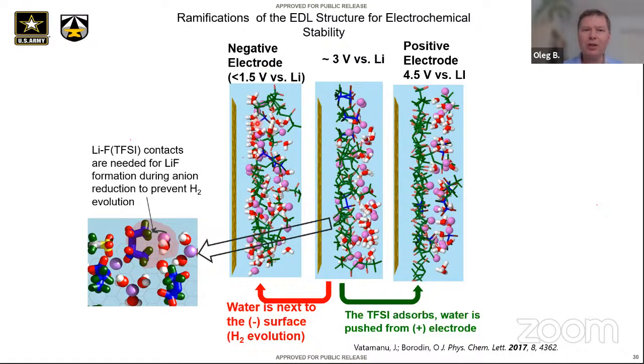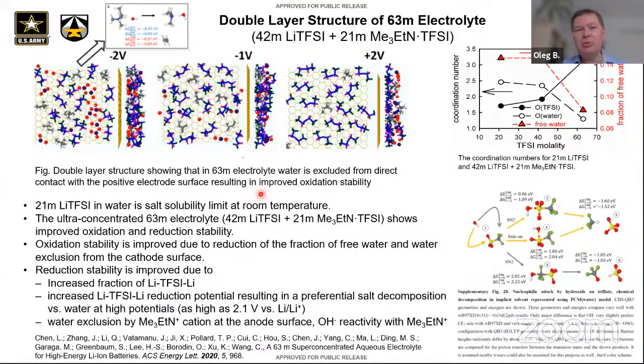However, on the negative electrode, especially if potentials are very negative, if you look at what the previous seminar speaker Axel talked about, water at platinum interfaces is really ripe for abstracting a proton, transferring it to the surface, and having a hydrogen evolution reaction. So that's a problem. Therefore, we need to form an SEI for these systems. Or how can we improve on SEI?